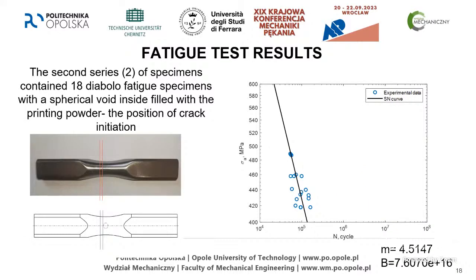Beside this, we have also the fatigue curve for the specimens with the void inside. As you can notice on this picture, the crack didn't occur in the center, but as you can see by the red lines, it has occurred a little bit to the side of the void, right? And it appeared every time around this area. It never appeared in the center where we presumed would be the weakest area, right? Because there is this void, it's filled with powder, but it's still the void. This should be the weakest area.